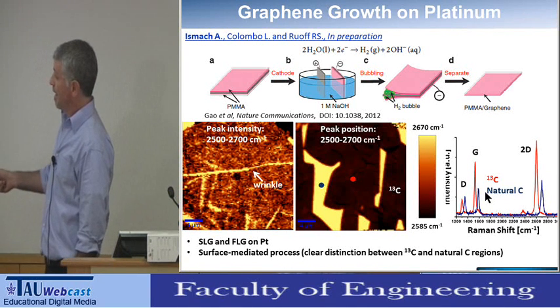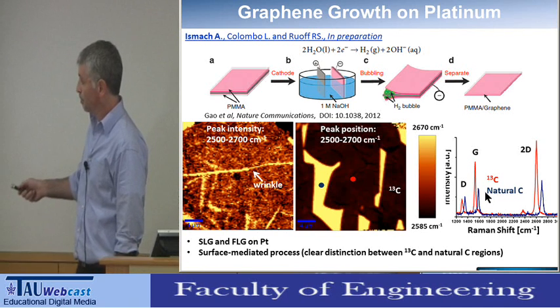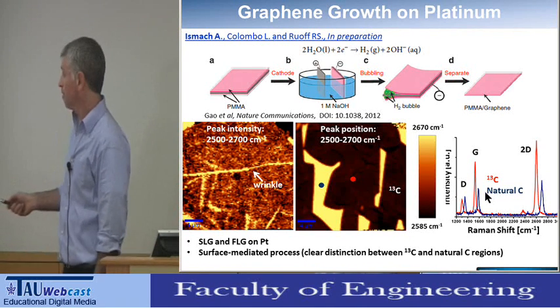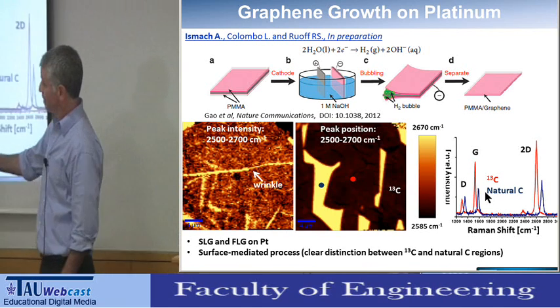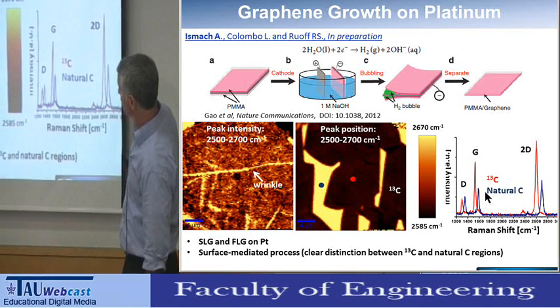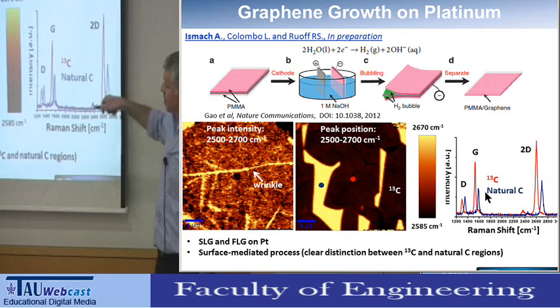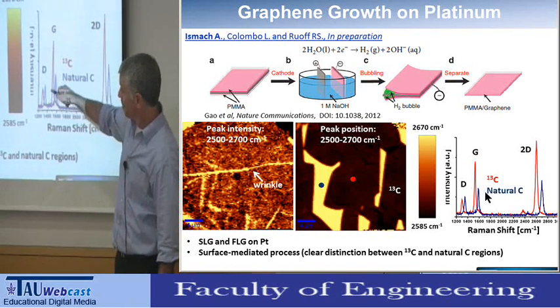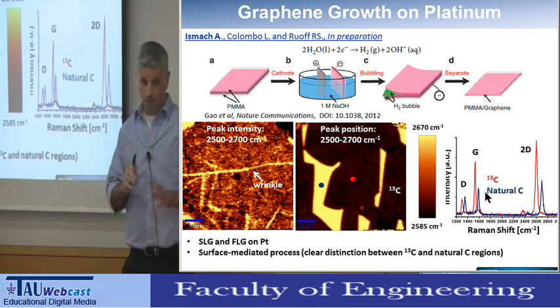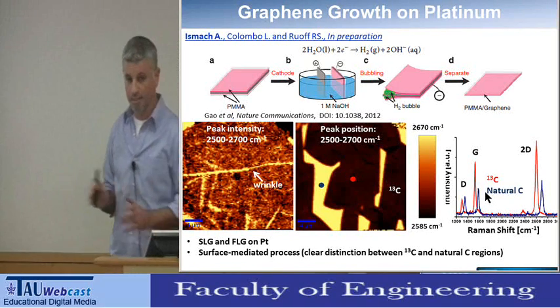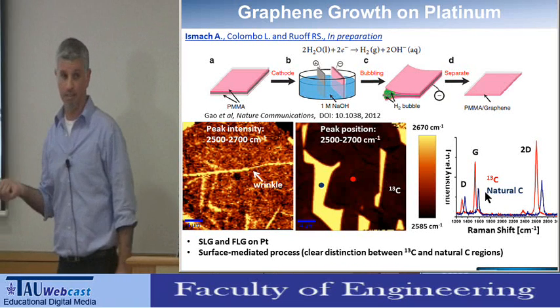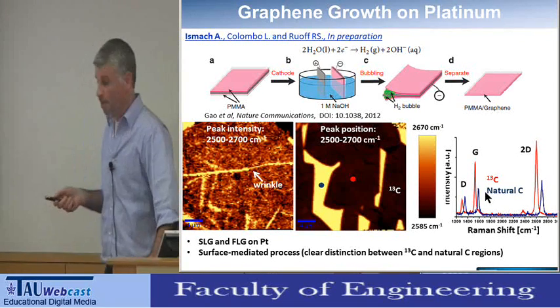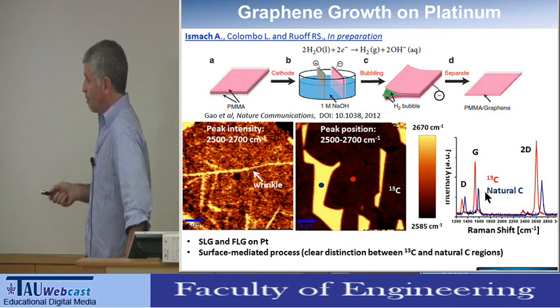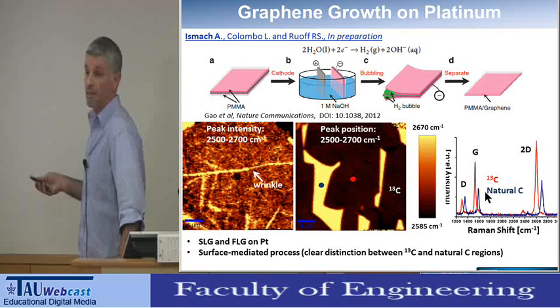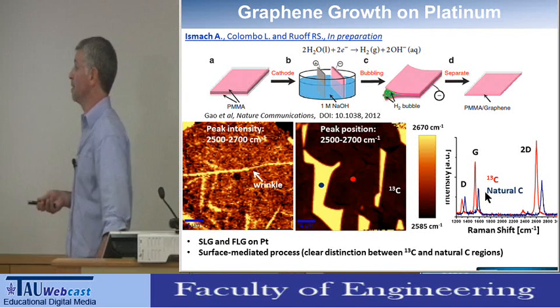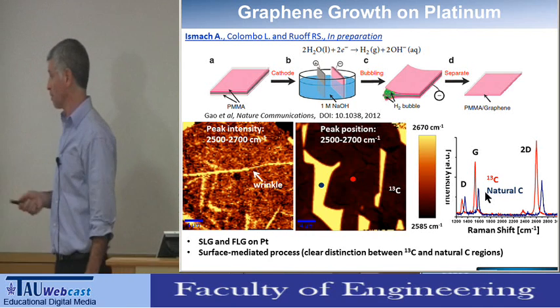Here you can see a mapping of graphene that was synthesized on platinum. Here you can see the mapping with the intensity, in this case of the 2D peak. But here you can see the same mapping in the same area with the position of the 2D peak. And you can again identify very easily the different regimes with the C12 and the C13 carbons, suggesting that the growth here is by a surface process, even though the platinum has a higher solubility of carbon in it at the temperature of the growth.